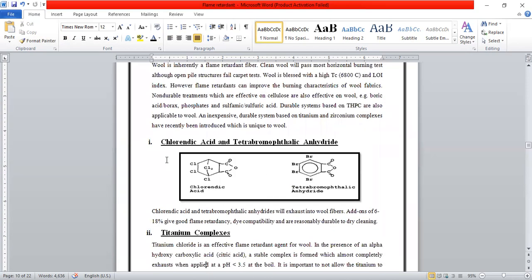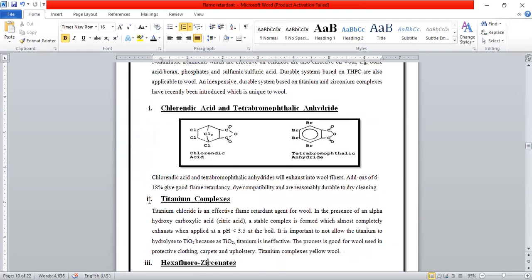First one is chlorendic acid and tetrabromophthalic anhydride. Chlorendic acid and tetrabromophthalic anhydride will exhaust into wool fibers. Add-ons of 6 to 18% give good flame retardancy and dye compatibility, and are reasonably durable to dry cleaning.